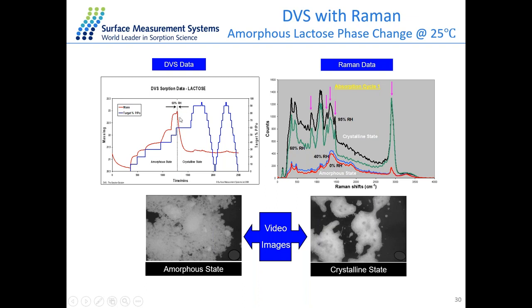And in this case, because of the change of our sample going to a crystalline state, what we're seeing is that we have more of a lattice structure being formed. And since the lattice structure is quite tightly packed, we're actually losing this mass uptake. That's why we see a drastic drop in the uptake of mass. And this change is quite constant with increasing relative humidity here. So we can see that there's definitely a change from an amorphous to a crystalline state.